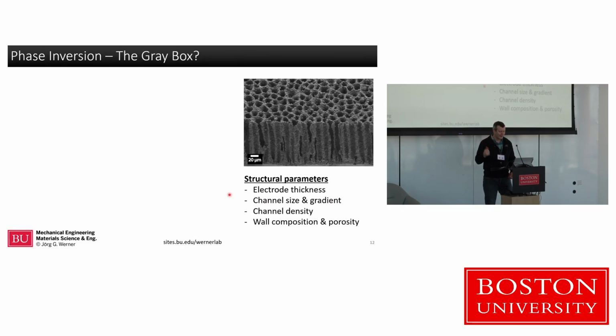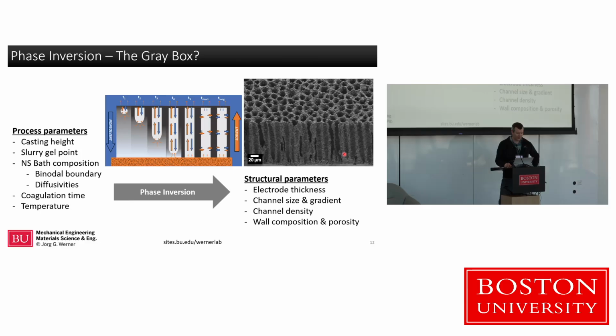Now, if we look at our electrodes, we want to modify these structural parameters: how thick the electrode is, how big the channels are in diameter, and if there's a gradient or not, how many of these channels there are, and again, what's in the wall, especially the porosity of the wall. And we realized that a lot of the process parameters of this really easy polymer processing fabrication method impact all of these things. And we really experimentally over the last 5 years have figured out a lot of these things.